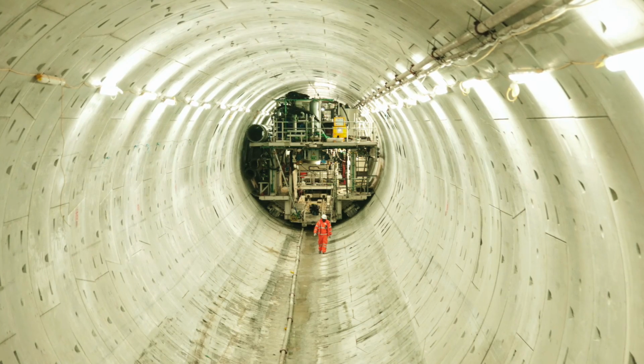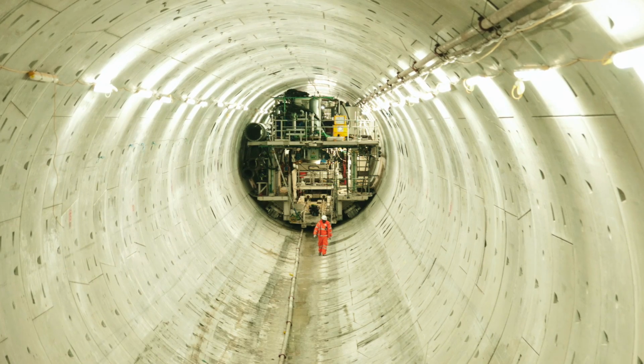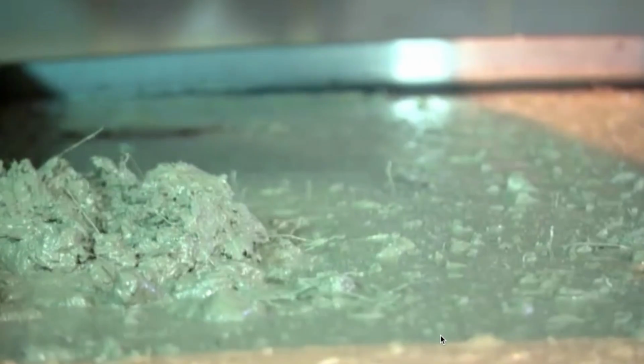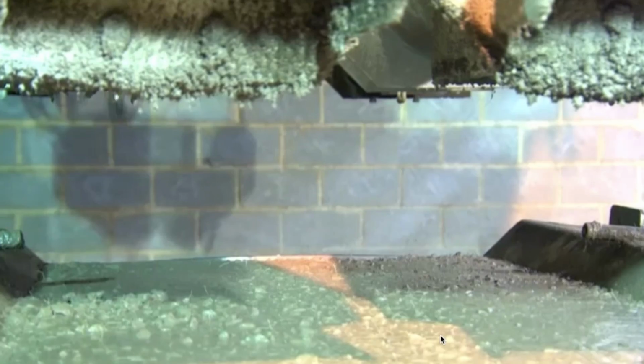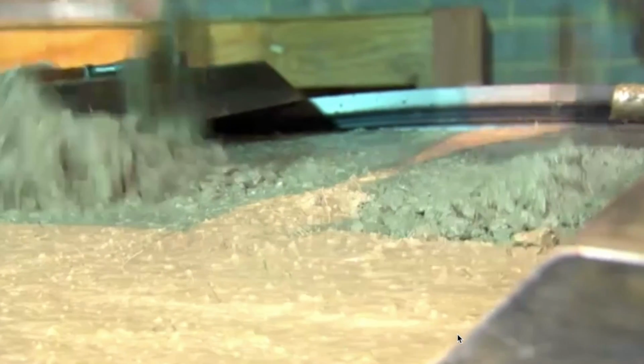segments. The fact that nowadays, in segmental lining, fibres are more and more used, that means that people are happy with what they have done in the past. And also, as to durability, there is no doubt at all. Sometimes they speak about these fibres possibly corroding, but again, if the mix design has been designed in a proper way, such that you have enough fine material to cover all the fibers, then you avoid that problem of corrosion. And in fact, a fiber that is at the surface is not contributing to the strength either, because it has not so much bond to the concrete. It's not taking over the load from the concrete into the fiber.